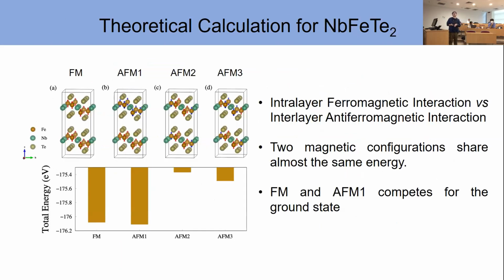And we have our theoretical calculation for DFT to illustrate the result of our experiment. From the calculation, we find that there is an intralayer ferromagnetic interaction versus interlayer antiferromagnetic interaction. Among these four different magnetic configurations, two of them share almost the same energy, and they are lower compared to other configurations. We call them FM and AFM1.